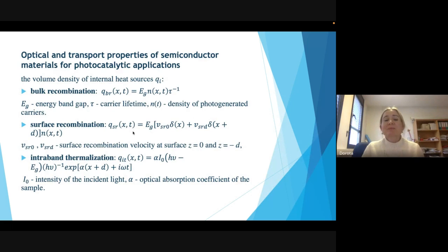It also has more sophisticated applications. One of them is the determination of optical and transport properties of semiconductor materials. In such a case, when the excitation radiation is absorbed, the absorbed radiation is released back in the form of heat. We need to take into account that we produce within the sample internal heat sources that result from the bulk recombination, surface recombination, and the so-called intraband thermalization.